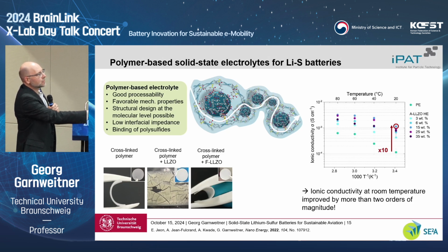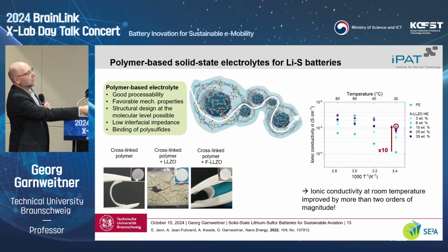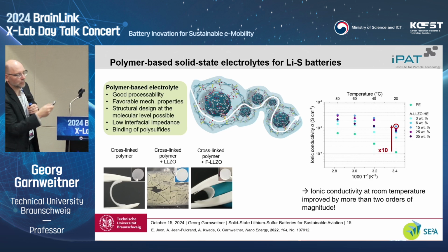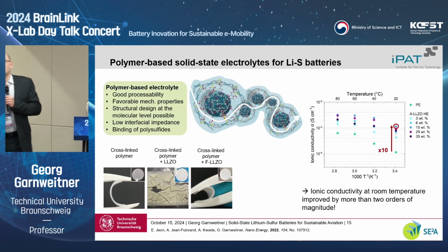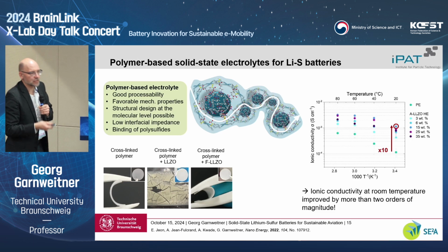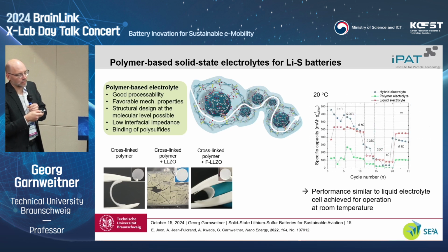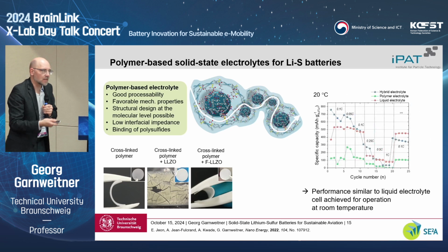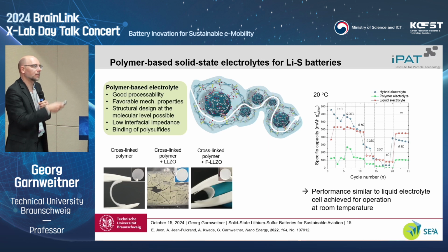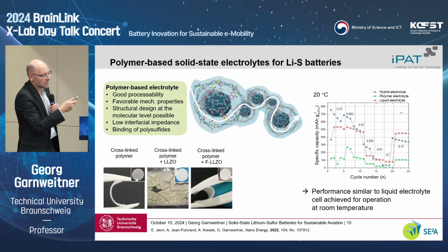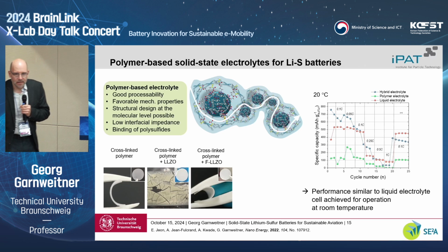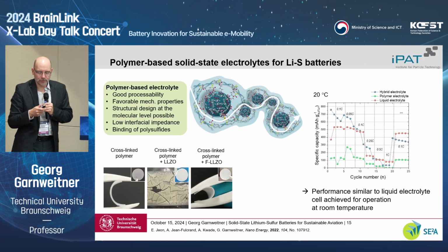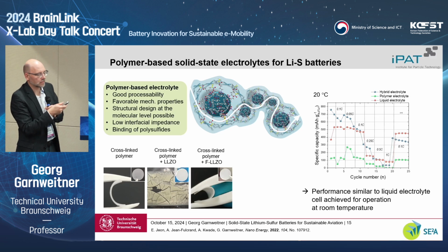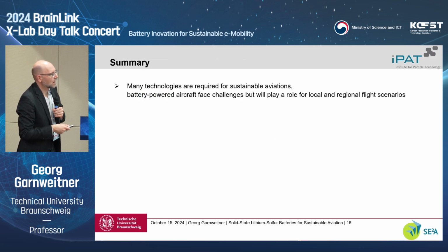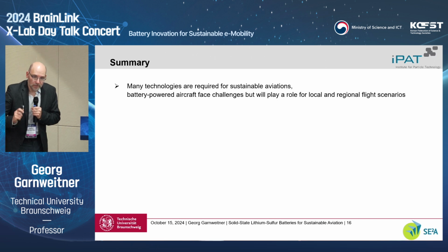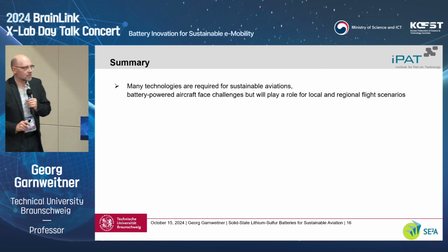So here the scale is changed, and from 10 to the -4, we increase to more than 10 to the power of -3 Siemens per centimeter at room temperature, and this is basically perfectly fine for operation. And we could see that we then have a battery that we can operate at room temperature that has a performance similar to a liquid electrolyte, although you see that the rate dependency is still quite strong, which is not due to the solid electrolyte, but due to the cathode configuration that we used in this system. Okay, I will talk about it in more detail in the next days' discussions.